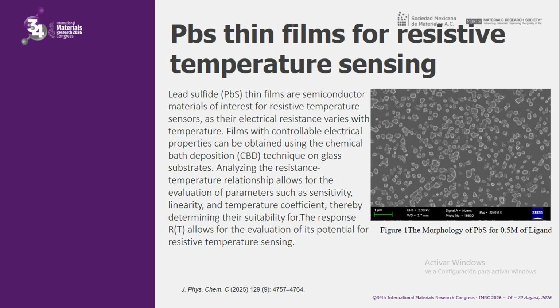PbS films for resistive temperature sensing. Lead sulfide PbS films are a semiconductor material of interest for resistive temperature sensors, as their electrical resistance varies with temperature. Films with a wide range of electrical properties can be obtained using the chemical bath deposition (CBD) technique on glass substrate. Analyzing the resistance-temperature relationship allows for the evaluation of parameters such as sensitivity, linearity, and temperature coefficient, thereby determining their suitability for the response. RT allows for the evaluation of its potential for resistive temperature sensing.